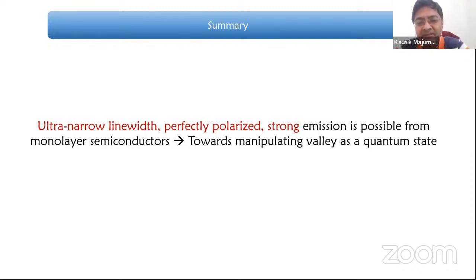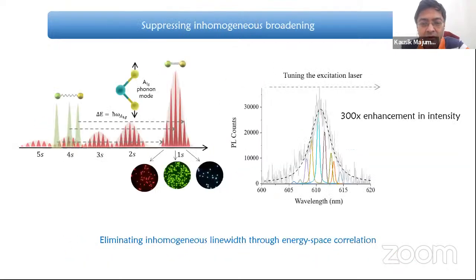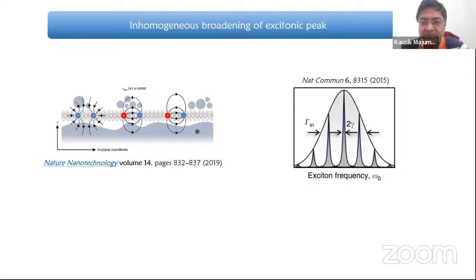So basically, what happens is that since you have many states that are coming, so when you see a 1s state, if I go back to let's say this cartoon diagram, you can think about it as you have several 1s states which are spatially localized at different points under your laser spot, right? Now, if it is coming through multiple phonons, you end up exciting all of them. And that's where the problem is. So while emitting, everything emits, and you basically get a broad spectrum.